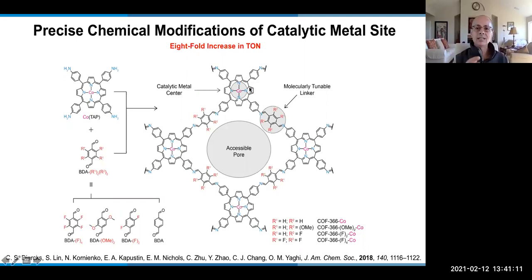And what this is telling us is that this catalytic center is really electronically wired through the linker, okay, by virtue of having these linkers between them. They're really not just fixed in position in the network, but also electronically wired, and any change that you make here in terms of the electronic character of this alters the electronic character of the catalytic site. So I think that this is taking advantage of the versatility of molecular chemistry and really translating it into a versatility in a solid or a material.